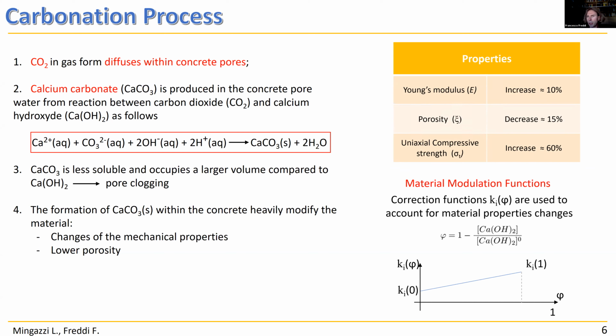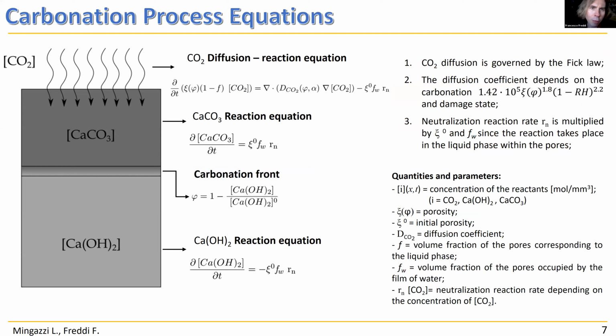I consider, in the simplest relationship, a linear variation of these properties, the porosity and the two mechanical properties, stiffness and strength, as a function of the calcium hydroxide concentration with respect to the beginning. But the most important thing for this problem is the reduction of the pH. Now let's move to some equations that are for mathematicians. For the diffusion of CO2 and reaction within the concrete element, I'm considering a classical reaction-diffusion equation based on Fick's law.